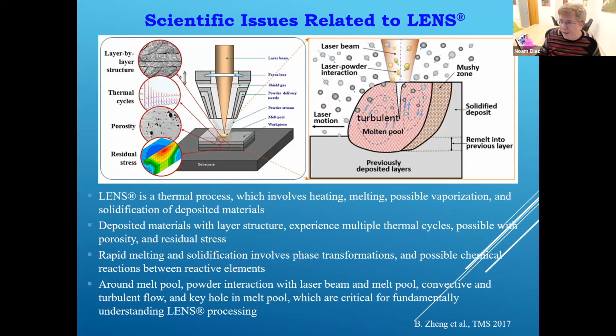Here you can see some schematics of the physical process. On the left-hand side, the top one, the layer-by-layer structure, and different orientations of the scans result in these different shapes that you see between layers. We have here thermal cycles that affect, of course, the microstructure and the resulting properties. We need to account for the porosity. Typically, you will have higher porosity at the interface between the building plate and the sample. But then, of course, you can also get significant porosity in the bulk material, depending on the parameters that you are using. So this is one of the challenges in general that one has to optimize.